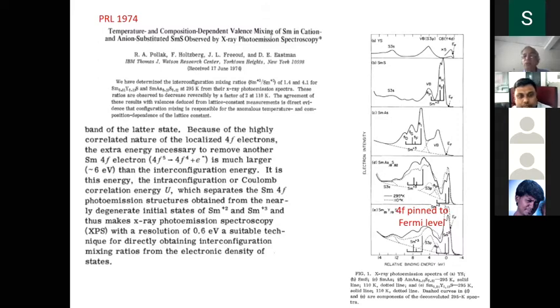On top of it, you could find the 4f level is rather close to the Fermi level. In other words, energetically it is lying at the Fermi level, so the electron can really go to the top of the Fermi level and come back. If it is deeply localized, the 4f electron energy will be far away from the Fermi level, and therefore you cannot expect the electron to go out. In this case, they find it really is pinned to the Fermi level. So this is how they proved spectroscopically that both valence states are present.